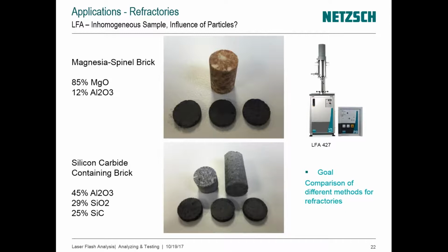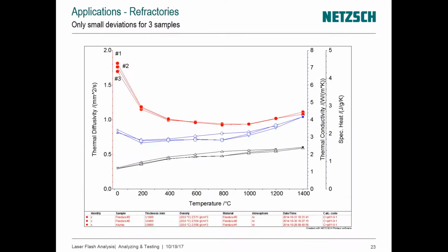There are two things we'll have to be using in those cases. First of all, they are bricks, ceramics, so slightly porous. We have a model for that, and they will tend to be also semi-transparent. We have the appropriate model for that too. Here are the results obtained with three specimens of each type for each brick. The reason we show three different specimens is because the specimens are non-homogeneous. Depending on where the samples are chosen from that block, the diffusivity or the components might be slightly different. So it's good to have a series of specimens and see how those results vary from sample to sample.